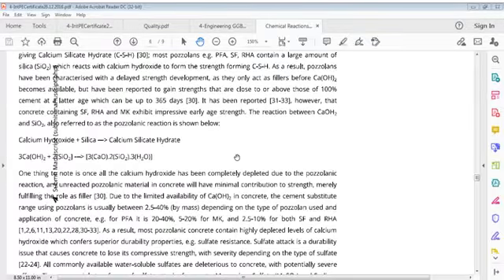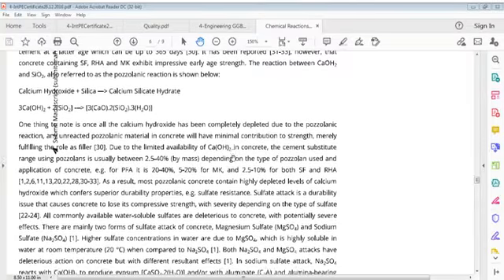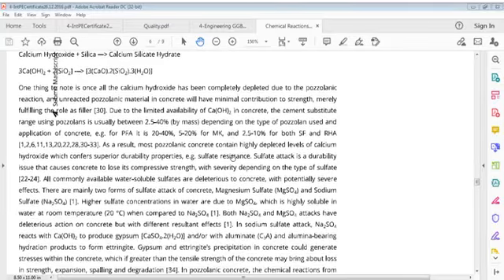It has been reported, however, that concrete containing SF, RHA, MK exhibits impressive early age strength. The reaction between Ca(OH)2 and SiO2, also referred to as the pozzolanic reaction, is shown below. Calcium hydroxide plus silica gives you calcium silicate hydrate: 3Ca(OH)2 + 2SiO2 gives 3CaO.2SiO2.3H2O.